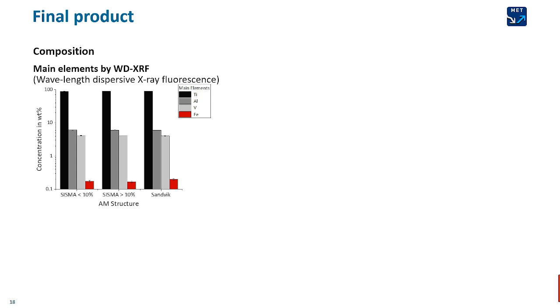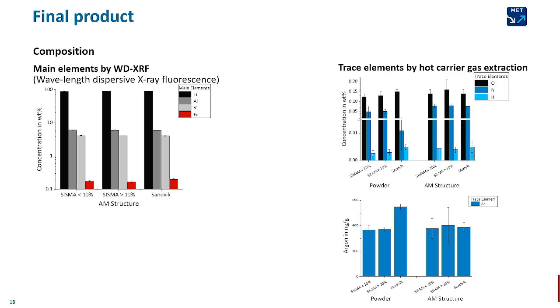Powders might have some elemental distributions. For instance, how much iron do we find in a powder? So here, Sandvik had in this plot a little bit more iron than the other one. Or there might be some differences within hydrogen content as well. So hydrogen can lead to embrittlement. So we want to have hydrogen below a certain limit to not face hydrogen embrittlement at the end.